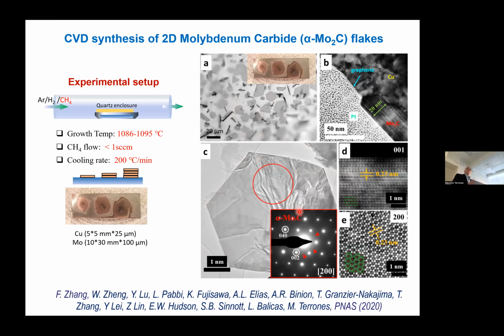They are monocrystals and very thin. These ones are embedded in the copper, and they could be as few as several nanometers thick, and could be large, right? Several microns in length. So we can grow these carbides. What can you do with carbides? You can start sulfurizing or chalcogenizing the carbide, so we can start making these heterostructures.